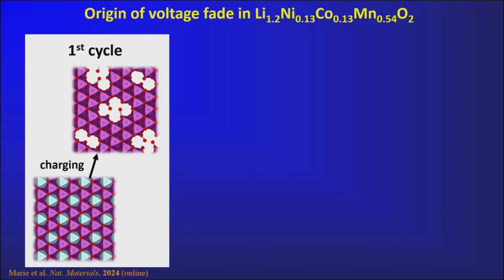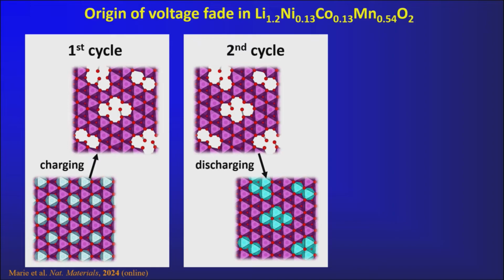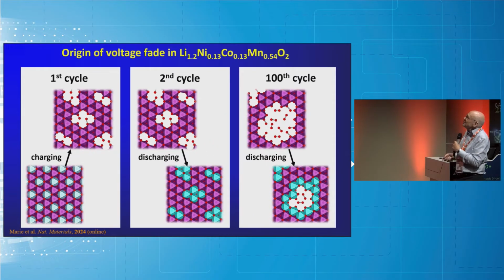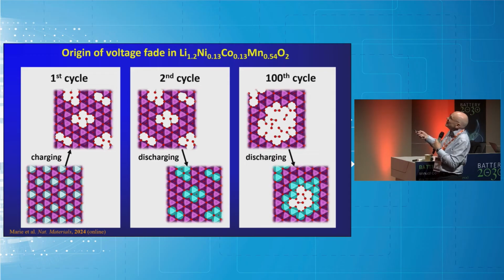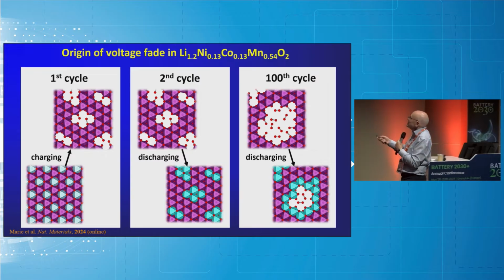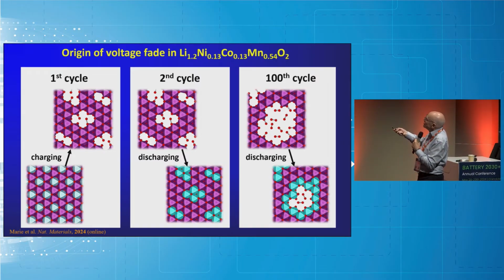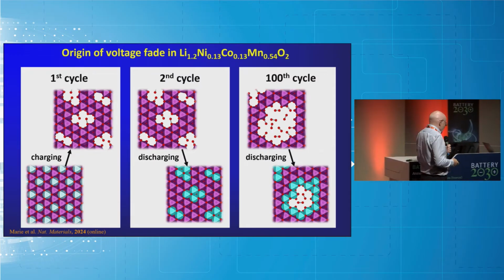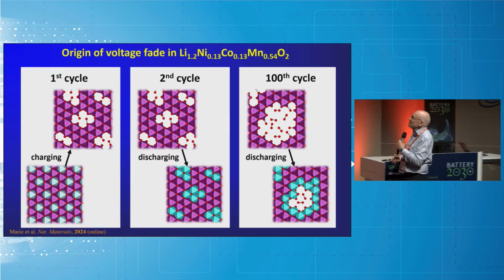Here's the honeycomb structure again. This is what I've already shown you. Charging, the first cycle, you get your nanovoids with two molecular oxygens in each. Then you put lithium back in again. On the 100th cycle, you're getting voids that are much bigger with a number of oxygen molecules in there. When you discharge, you put lithium back in here, but of course the lithium ions tend to fill up these positions, so you almost get a coating of just lithium oxide around the inside of the void, which of course makes electron tunneling to reduce the molecular oxygen even more difficult. And some of that molecular oxygen just doesn't get reduced back to oxide ions. Therefore you get this accumulation of O2 in the bulk.